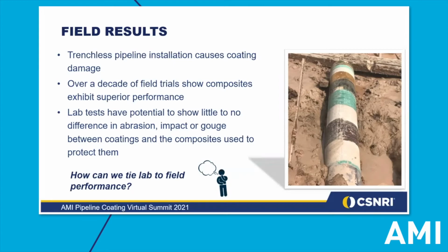Well, first of all, many of them were already pulling sacrificial pipe for visual inspection, and they needed a solution which they didn't have. So it was easier for them to say, we'll look at this on our visual inspection piece. Composite material has proven to be a more reliable source than pipeline coatings alone, based on the results observed in numerous HDD thrust bore and direct pipe projects, and they were used on many of these in the field as trial samples. Lab results showed little or no difference in abrasion, impact, or gouge testing between these two types of materials, while the field trials showed very different results.